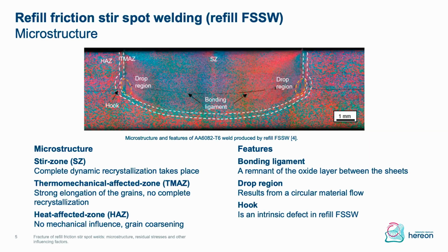The features frequently named in literature are the bonding ligament, which is an oxide layer which remains between the sheets, as you see in the picture. A drop region, which is caused by the circular material flow, and a hook, which is an intrinsic defect in refill friction stir spot welding and is known as potentially strength relevant.